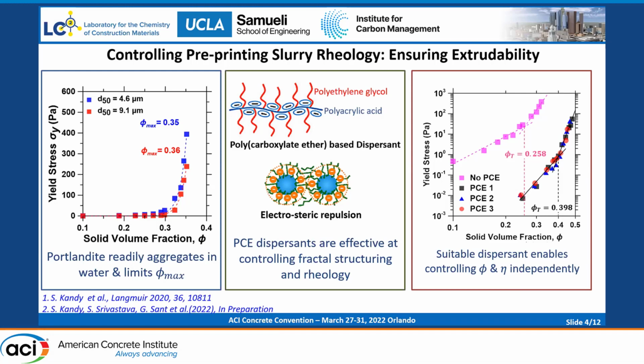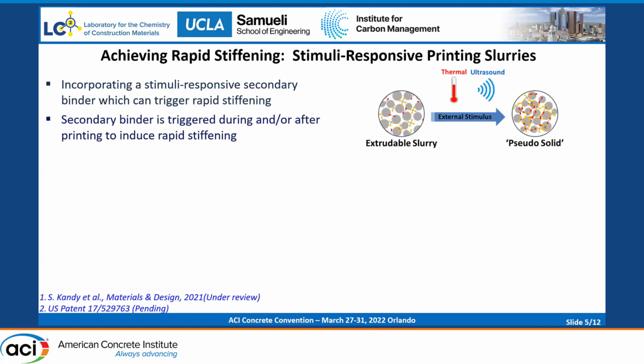So with this suspension, we'll be able to control both the solid volume fraction and the yield stress or viscosity independently. So now we have suspensions which are meeting all the pre-printing rheological requirements. How do we achieve this rapid stiffening? In the last talk, we have seen various methods to improve the stiffening kinetics in Portland cement-based slurries.